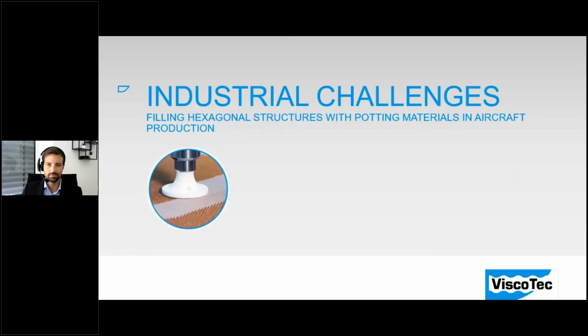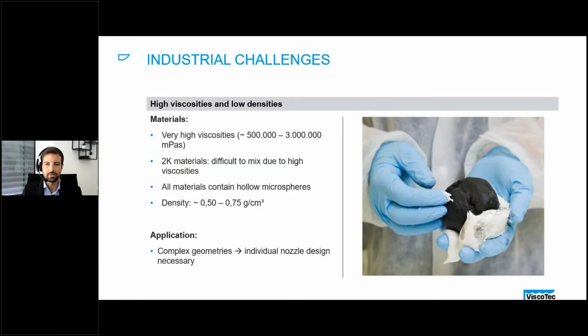So exactly what are the industrial challenges? As said, typical materials are very highly viscous 1 or 2 component epoxy resins. Therefore, viscosities even up to 3 million millipascal seconds are quite common. Furthermore, the materials are usually filled with a high proportion of hollow glass spheres in order to reduce the final density. Usual values are between 0.5 grams per cubic centimeter and even up to 0.75.